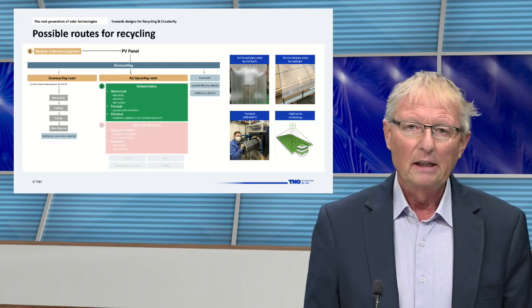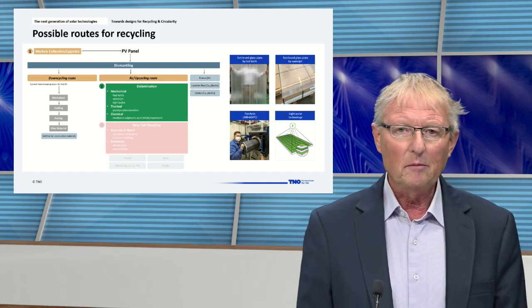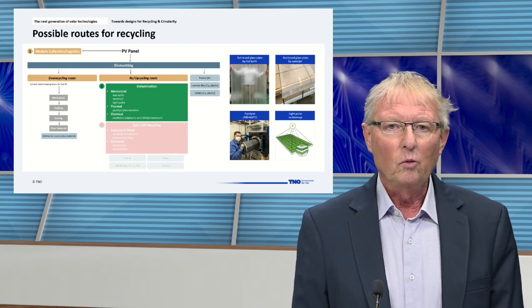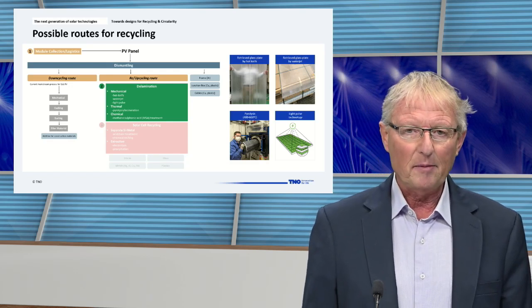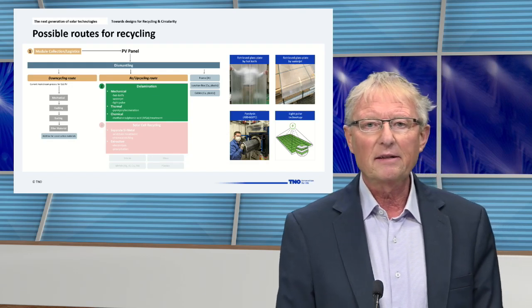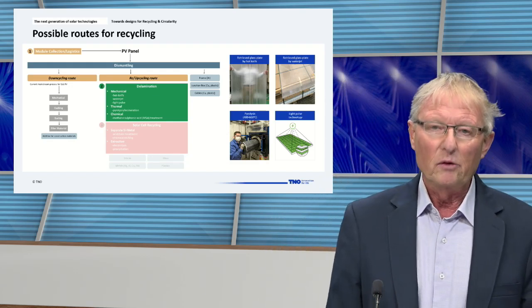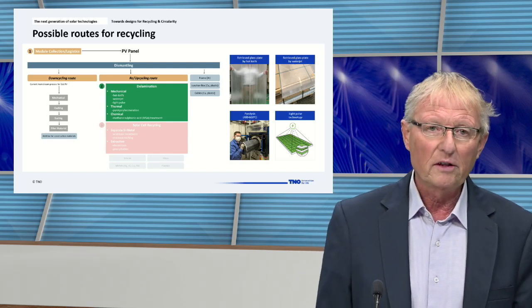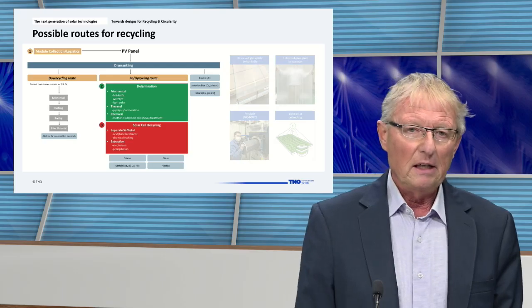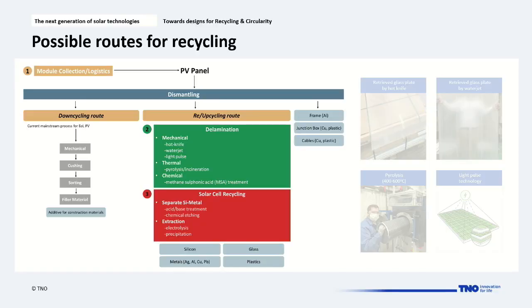We also can consider supercritical CO2 as a cleaning method. That leaves us with the solar cells in an encapsulant matrix and the backsheet, and that can be pyrolyzed at a low temperature of 400 to 600 degrees with exclusion of oxygen, and then we would have the solar cell available. Then we can take off the silver alloy of the contact material by nitric acid. But there is an environmentally more sound material for regeneration, and that is methane sulfonic acid, or the MSA treatment.